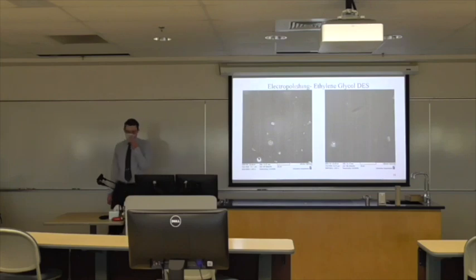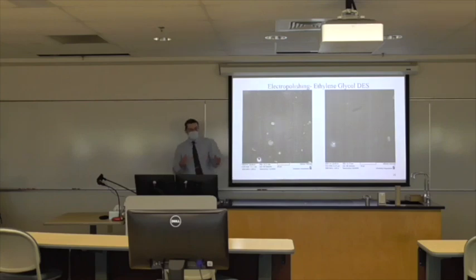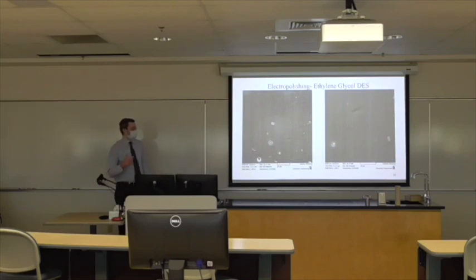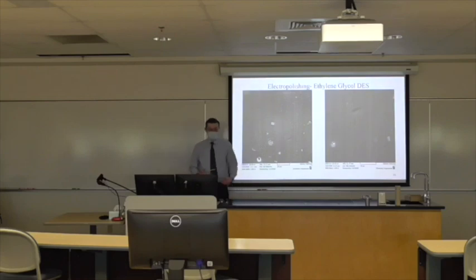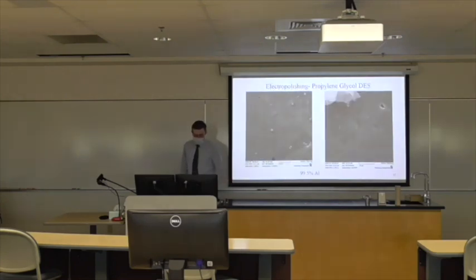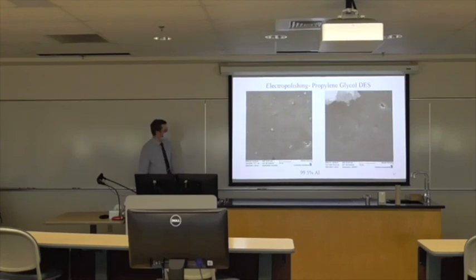However, those are under very specific conditions where you try and keep everything nice and contained. Under real conditions, especially in an open beaker, the 1 to 2 molar ratio does not work. So we found that a 2.5, or 3 ratio works better. So that produces the DS just fine. You mix the two things together in those ratios, and it makes DS just fine, especially with a little heat. But then electropolishing becomes a little more challenging because the propylene glycol DS is less conductive than the ethylene glycol DS. And when we're trying to electropolish, we want to have something that's conductive. That required us to change the electric potential applied a little bit, but it still works at 10 volts or so. So at 10 volts, using just 99.5% aluminum, we get this polishing.